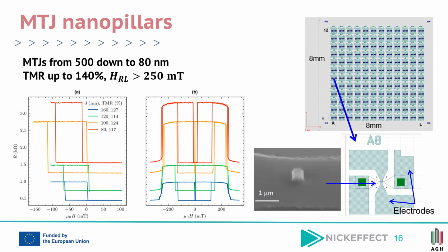After optimization of the MTJ stack at the wafer level, the structures were patterned into nanopillars with diameters ranging from 500 down to 80 nanometers. The fabricated devices were subsequently electrically characterized in order to evaluate the stability for STT MRAM applications.